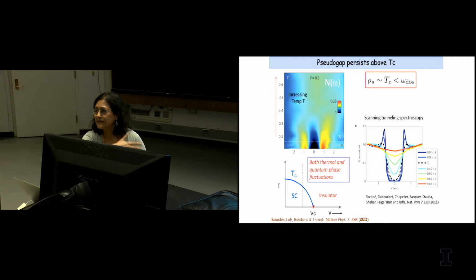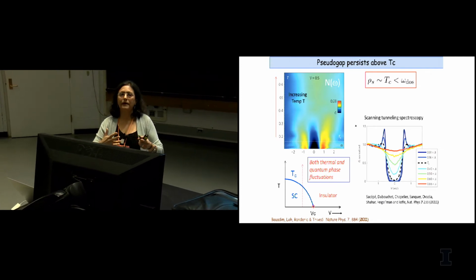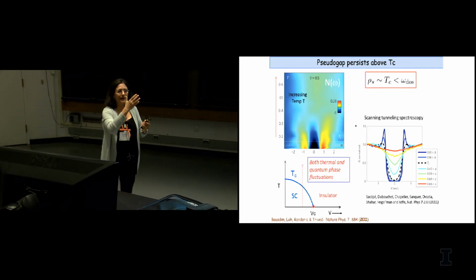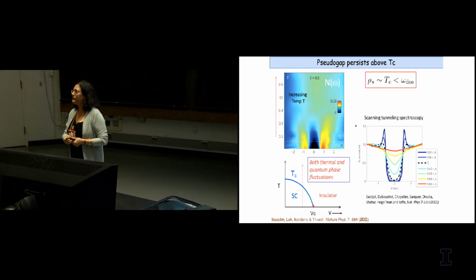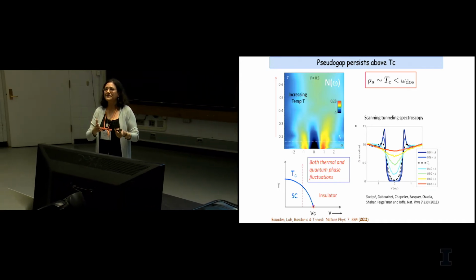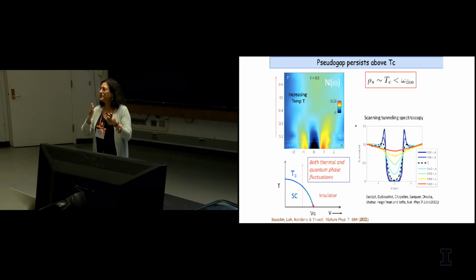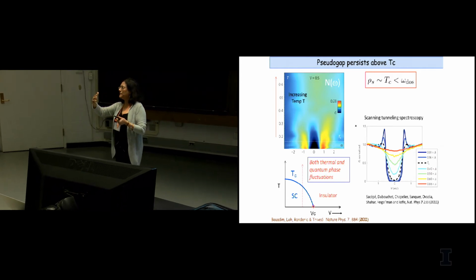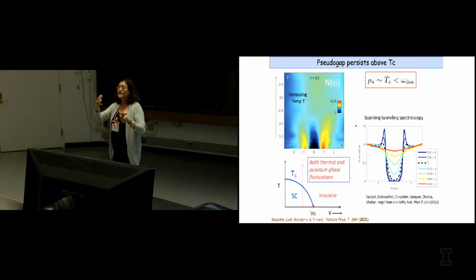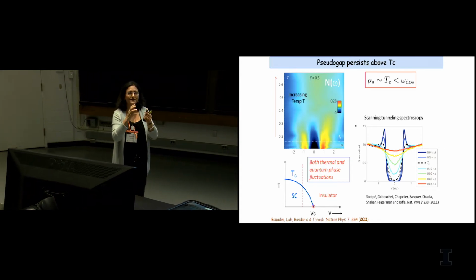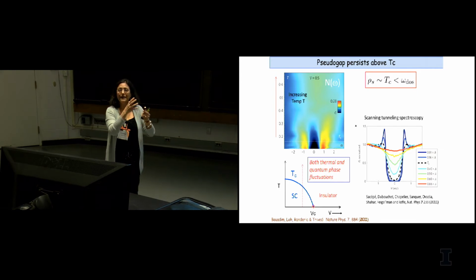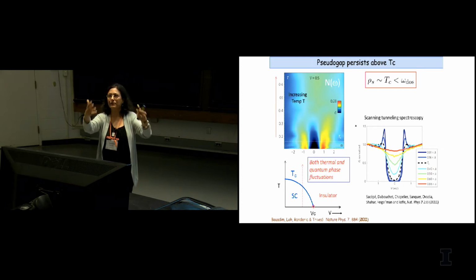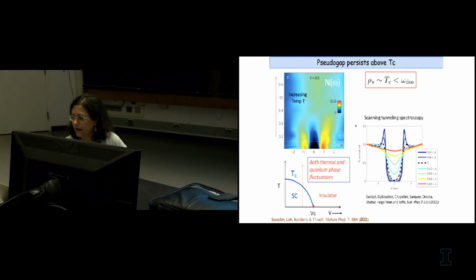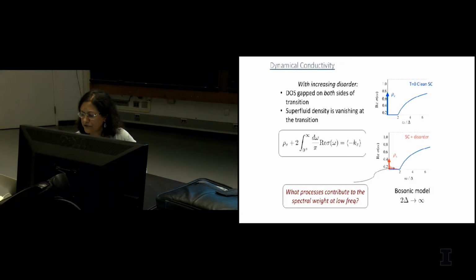And in this case, Mohit and his collaborators, following up on several of Tony's works on the BCS-BEC crossover, had shown that as you go toward the BEC regime, you have pairs still existing in the normal state. There it was happening because of strong interactions that were shrinking the size of the pair. Here it's disorder that is shrinking the size of the pair because of localization effects. And as a result, you still have existing pairs in the normal state. Okay. Let me kind of march on.